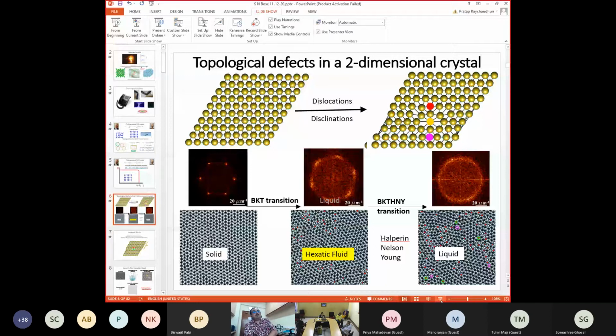And then it was Halperin, Nelson and Young who realized that for this state to go into a liquid, it will have to undergo another Kosterlitz-Thouless transition through another set of topological defects. So what is this other topological defect? This other topological defect is called disclination. A disclination is a 5-fold coordinated or 7-fold coordinated, or sometimes 4 or 8-fold coordinated point which does not have an opposite kind of nearest neighbor. So a dislocation is 5 and 7 adjacent. If these 5 and 7 coordinated points are far away, separated, then this defect is called a disclination. And this disclination destroys the complete order.